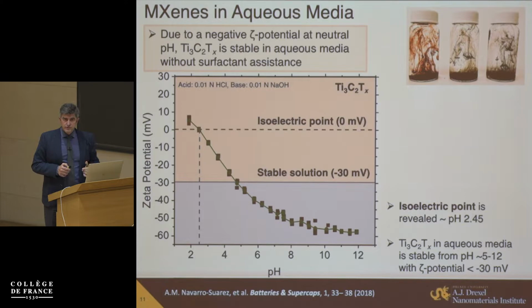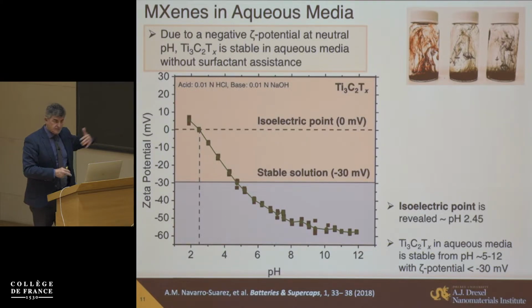Because this surface negative charge produced by oxygen and OH groups gives us from minus 30 to minus 80 millivolts zeta potential for some MXenes, so a high negative surface charge around the neutral pH region here. So basically these flakes form a colloidal solution in water, no binder, no surfactant, nothing needed. When you dry it completely, they basically stick back to each other. But also one important thing versus other 2D materials. When you reassemble, say, graphene, you can make graphite, or at least a disordered graphite structure. You cannot make MAX phase back. There is no bulk material with this composition because we now have this oxygen as a termination on the surface here. So it's a new material.